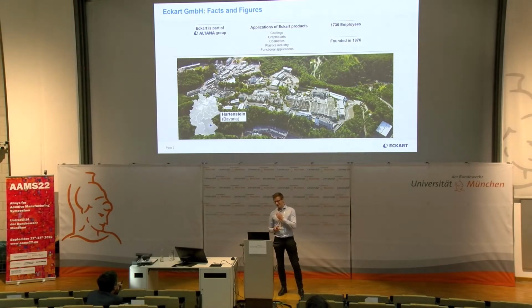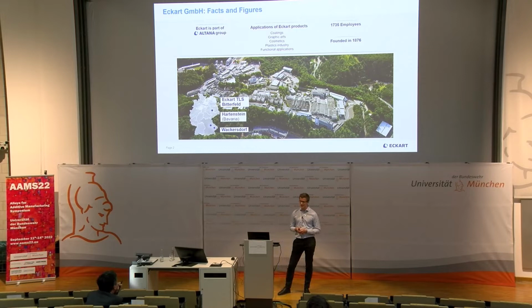So the headquarters are based in a very small village in Bavaria, in Hartenstein. This is also where my office is. And we have quite a few production sites and sales locations around the world, but two interesting ones are this one in Wackersdorf. This is where we produce about 10,000 tons of aluminium powder per year by gas atomization. And more importantly, maybe in this context, is Eckart TLS in Bitterfeld, formerly TLS Technik, which is where we produce only spherical metal powders specifically for AM.